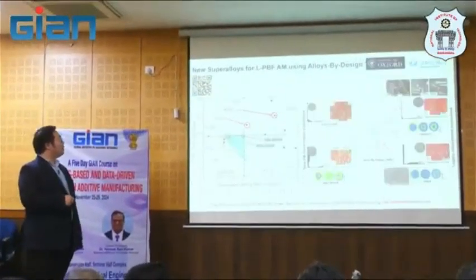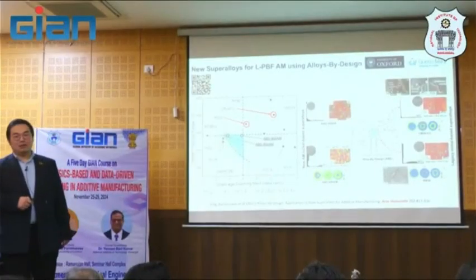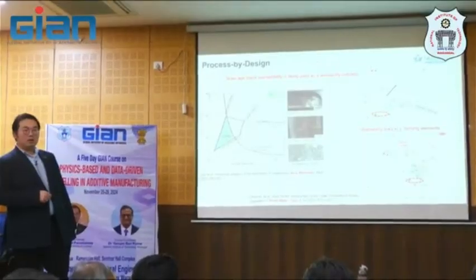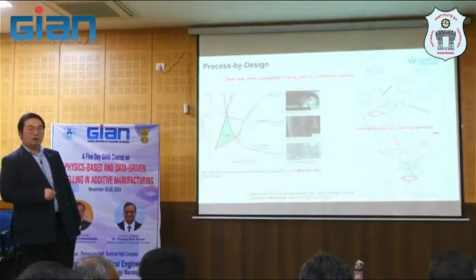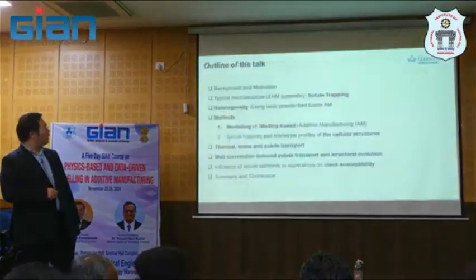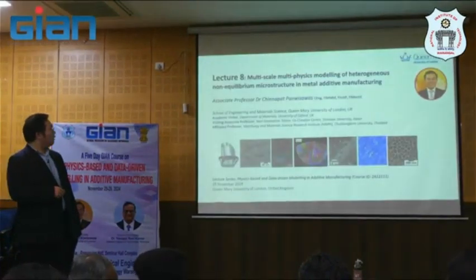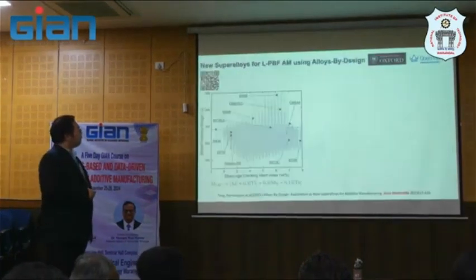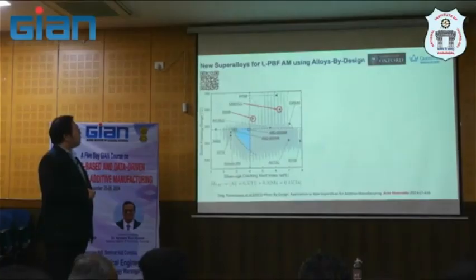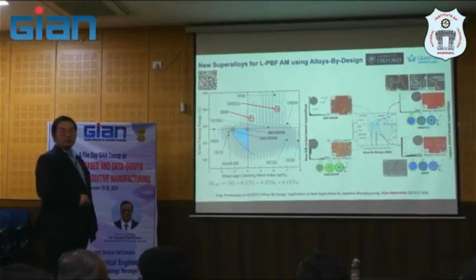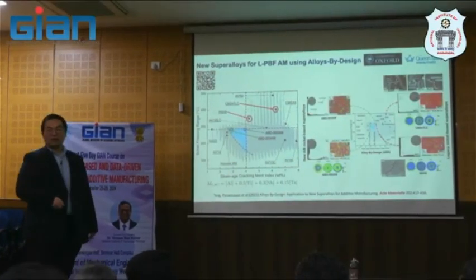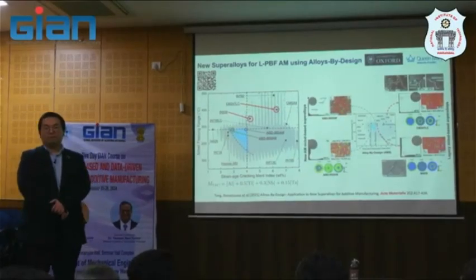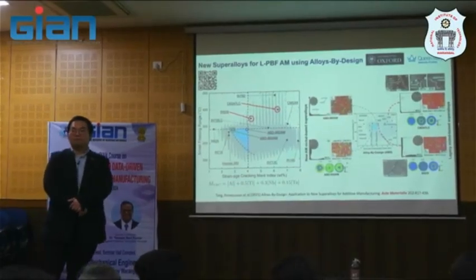Okay, I know this one. So this is the previous one, where the micrographs are showing reduced cracks: no cracks in the new alloy, cracking in Inconel 718. So the micrographs are showing hot cracking, and the index is strain age cracking.